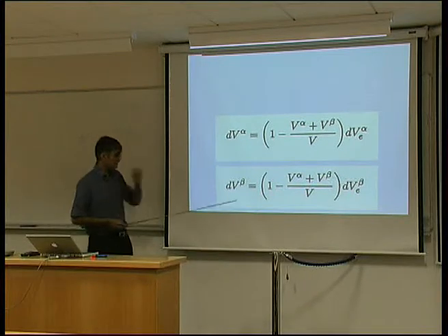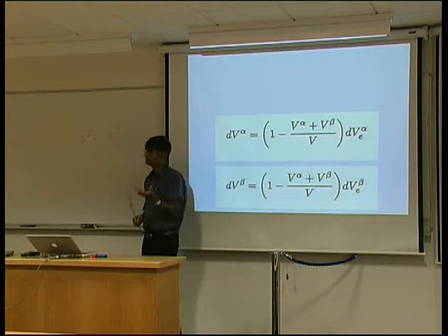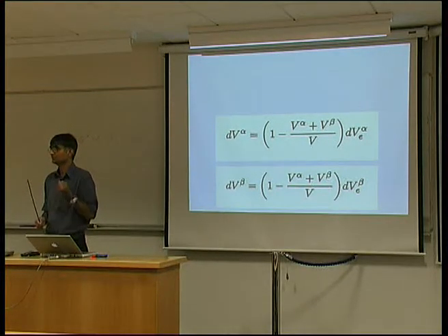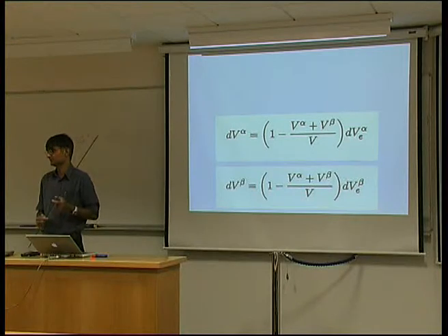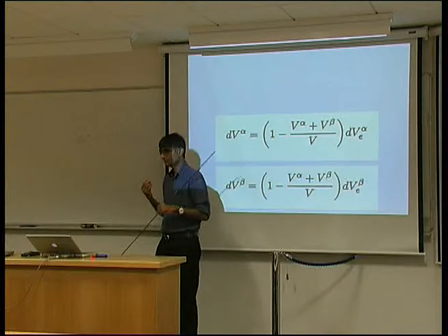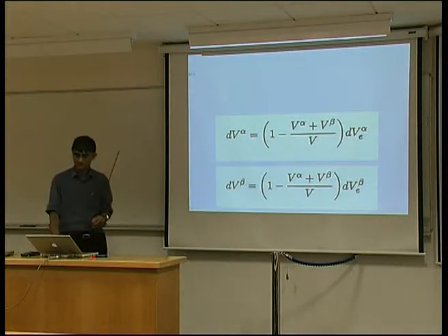And then you see, as the more stable phase beta forms, it will change the composition of the matrix and alpha will start to dissolve automatically. You don't have to put in any arbitrary parameters. And this has been a very big breakthrough in Avrami theory, in modeling real materials which have more than one phase precipitating at a time.